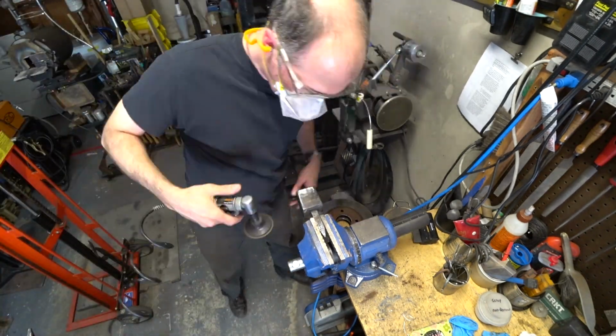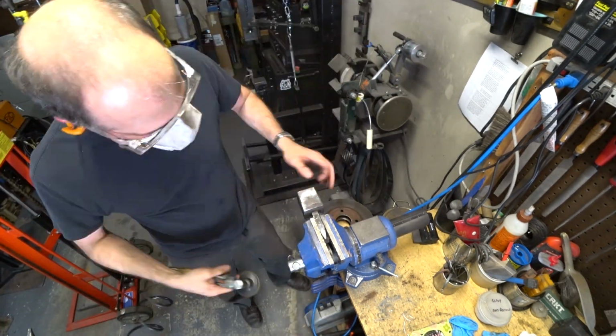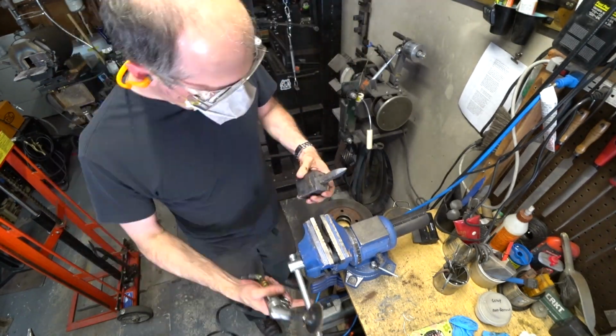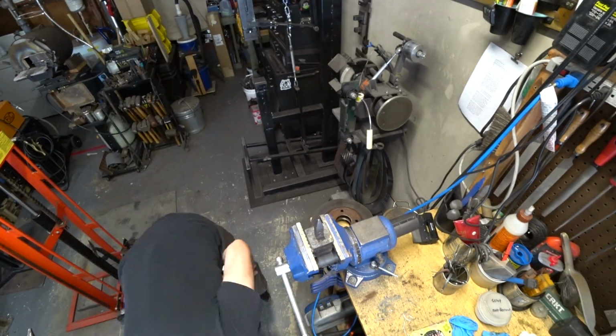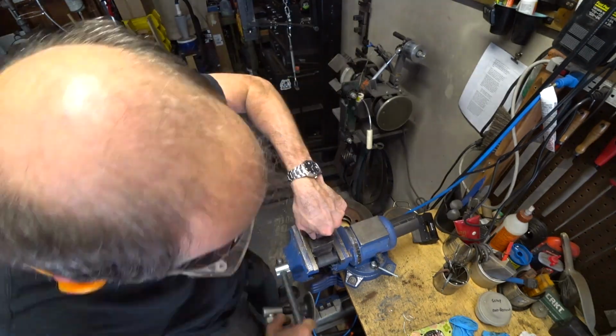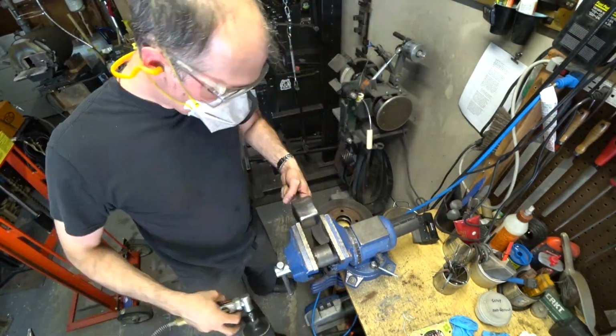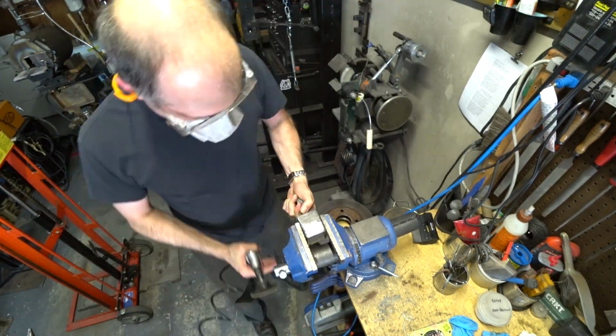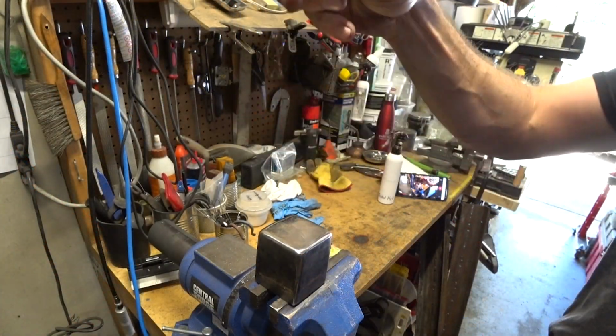I didn't perform a tempering cycle because I'm happy with the 55 HRC hardness. And also, you don't always need to temper case hardened material because the soft steel at the core actually makes the hardened surface much less brittle. And you can see that we actually get some decent little rebound off of this anvil.